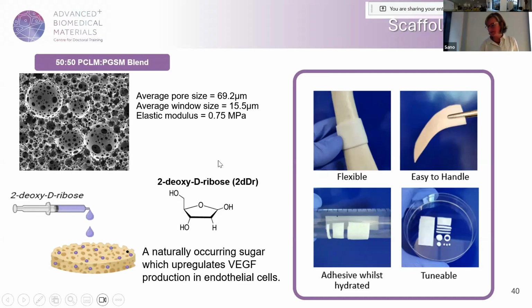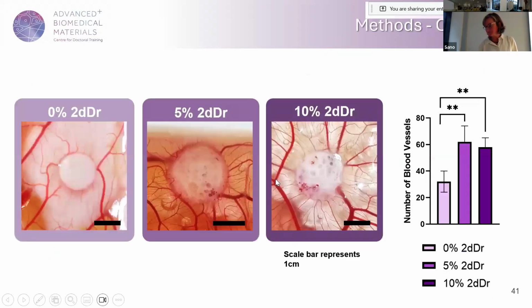So we can use a sugar, deoxy-D-ribose, that encourages blood vessel invasion. And that can be seen here on the CAM assay. So this is a really nice experimental model assay as well, if anyone models this kind of thing. Easier to access than a full animal model. You just break the egg, you put the material on the surface of the egg once the shell has been removed, and then because the egg's growing, it continues to make blood vessels, and they can infiltrate the material. You can count how many are coming and their size and diameter and everything. So we have done work with a mathematician in Oxford who models this kind of behaviour. So we can look at the number of blood vessels. We can see that our sugar is improving that, and therefore making it more periosteal-like.